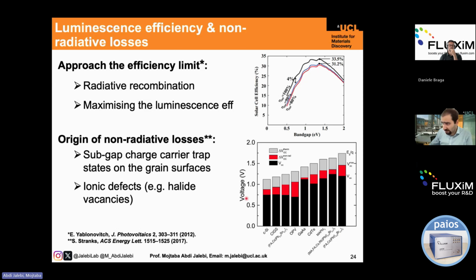This chart is also very important. It shows the maximum voltage we can reach in different PV technologies versus the voltage that we achieve. The black part shows how much voltage we have achieved so far, the red part shows the losses from non-radiative losses, and the gray part is the thermodynamic loss. It's interesting that gallium arsenide, which is the best semiconductor for PV devices and currently holds the records for PV, but is on the other hand super expensive to produce for conventional applications, shows the minimum non-radiative losses and maximum achievable VOC, or voltage. And for perovskite, it's interesting that by tuning the composition, you can minimize this red part, the non-radiative losses in your semiconductor.